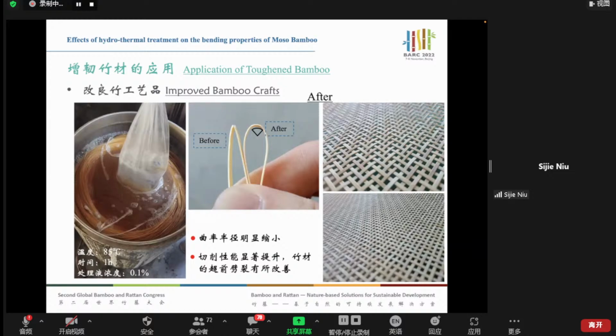However, after our toughened treatment, you can see before and after toughened treatment. On the left is before treatment, and on the right-hand side is the after treatment. You can see the radius of curvature is significantly reduced.